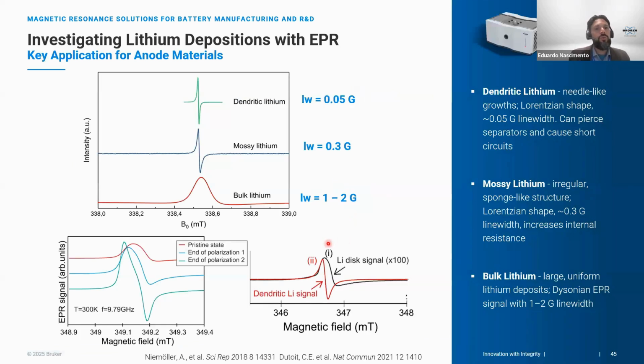Here I show only one application, which is very nice, where you can monitor anode material after cycling, because the EPR signal, the shape of the signal, can tell you about the state of the lithium, whether it's bulk lithium, mossy lithium, or dendritic lithium. So after some cycling, you can actually evaluate if you have some dendritic lithium formation.